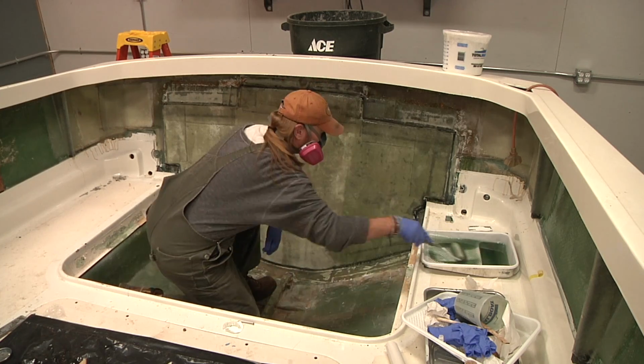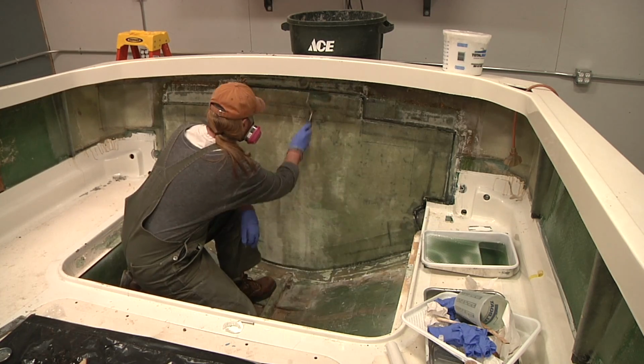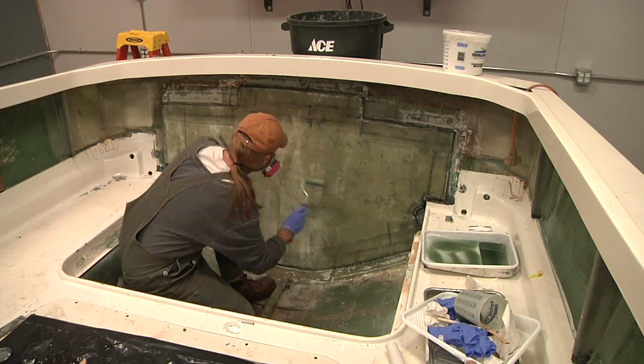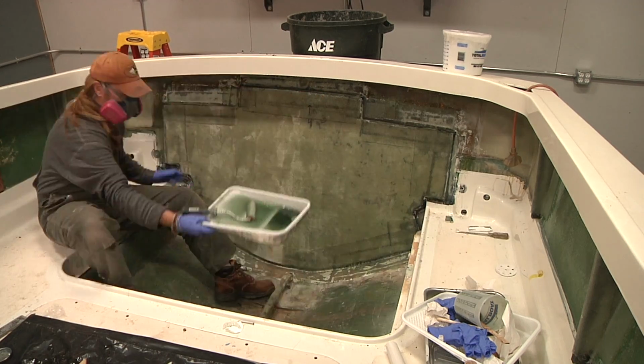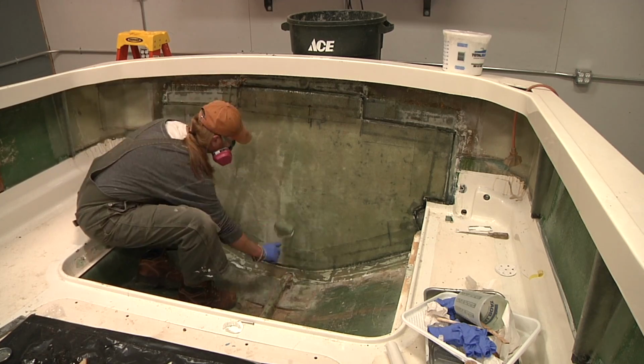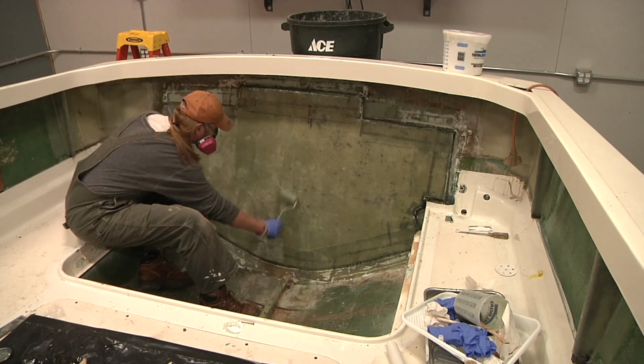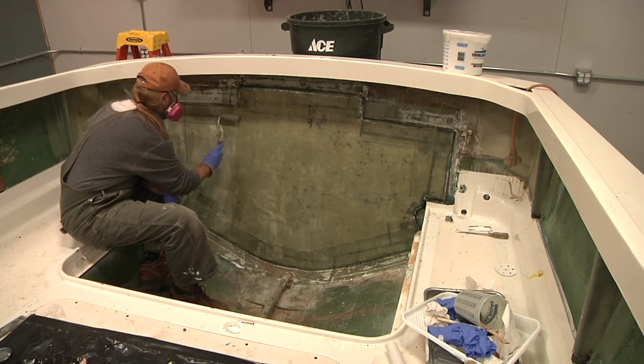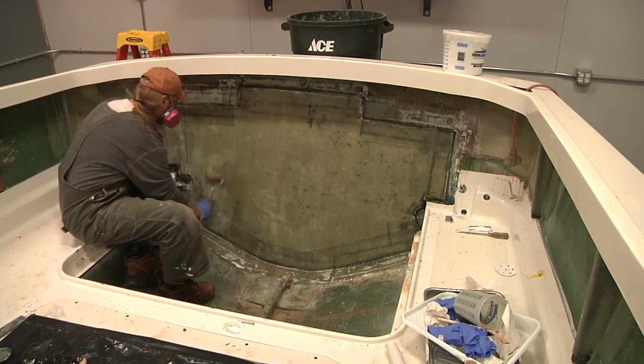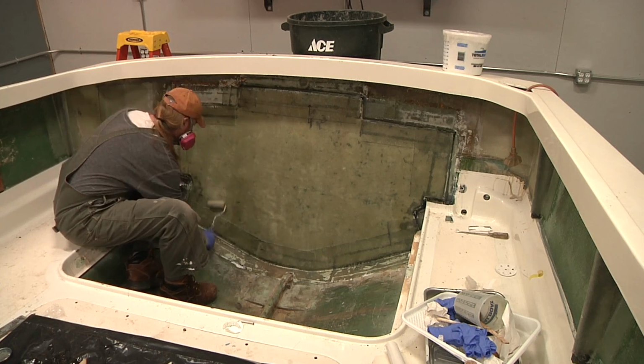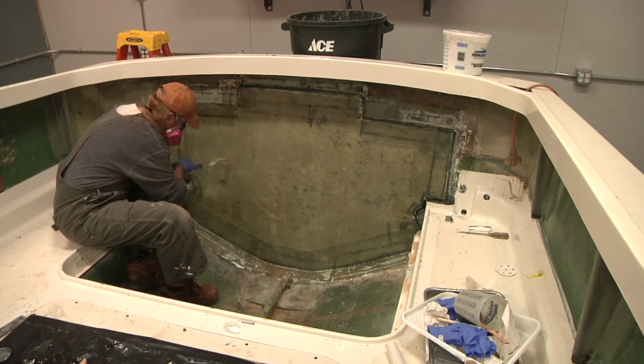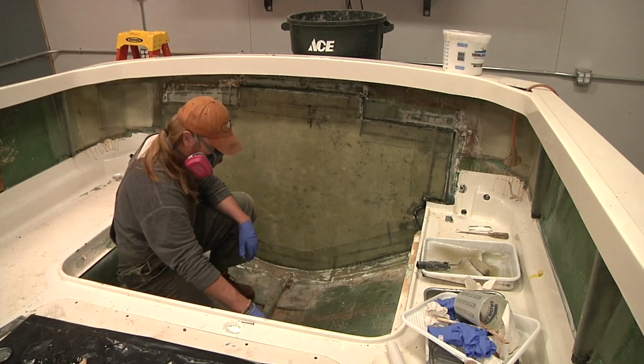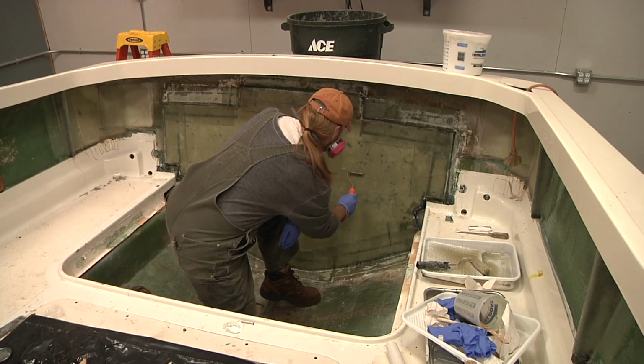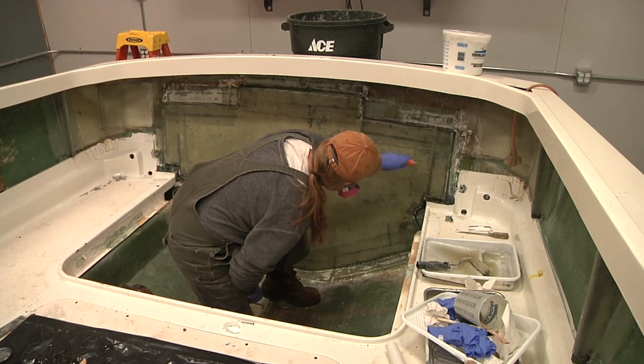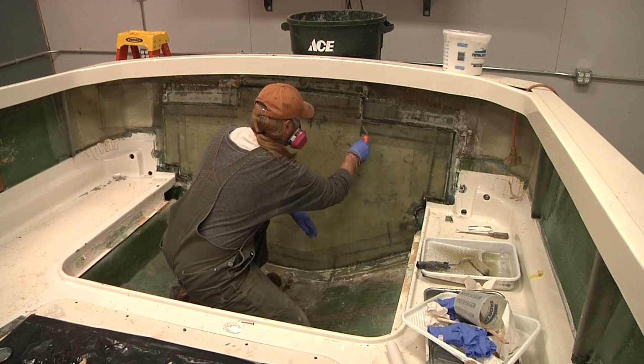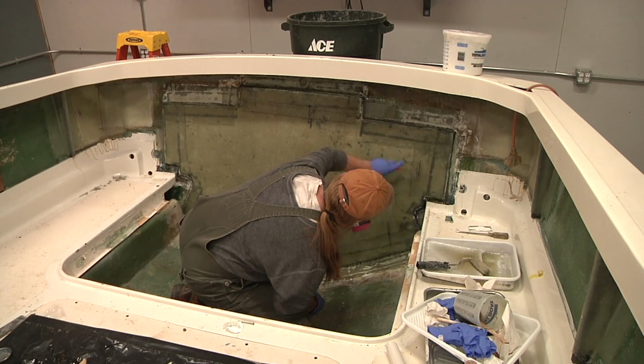And it was right about here that I realized that I may have gotten a little bit greedy trying to get this 4th coat on wet on wet on wet. Now, what I noticed was that the resin wasn't working into the glass anywhere near as easily as the previous layers. The glass itself, there's little ripples here and there. The glass itself wasn't shifting in order to work those ripples out anywhere near as easily as it was on the previous coats. And this layer was starting to get sticky very, very quickly, like to the point where it was pulling off little chunks of fuzz off of my roller.